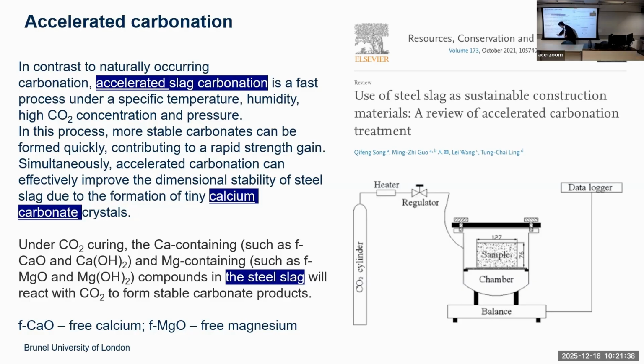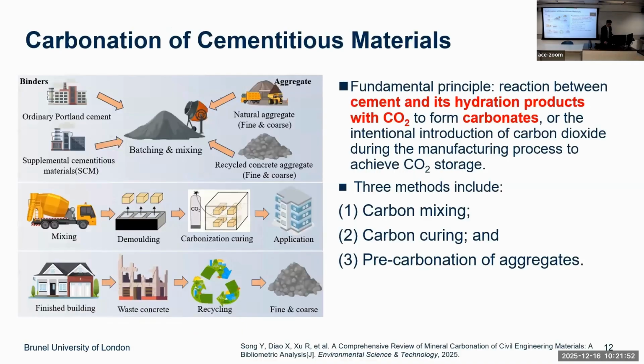They can also react with free calcium and free magnesium. Free magnesium can be a problem for many materials because it can cause expansion. So that's what we are using this technology for, developing this technology. Basically, carbonation of cement materials is the reaction between cement components, C2S, C3S, and calcium oxide, and hydration product CSH, with carbon dioxide, generating calcium carbonate, and also a small amount of magnesium carbonate. Magnesium carbonate and magnesium hydroxide are different phases, slightly more complicated than calcium. And we just had a PhD on magnesium oxide.